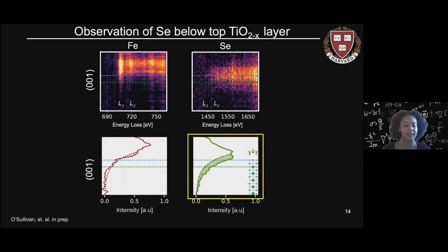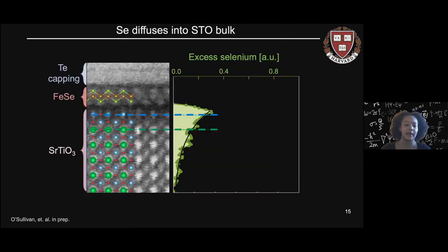So now we'll focus in on this selenium line cut. By directly aligning the selenium line cut with our STM image, as I presented earlier, we're able to quantify exactly how much selenium is diffusing into the strontium titanate bulk. You'll note here I've superposed the light green shaded area from the previous instrumental resolution correction. And I've also overlaid the blue dotted line representing the top layer of titanium and the green dotted line representing the top layer of strontium.